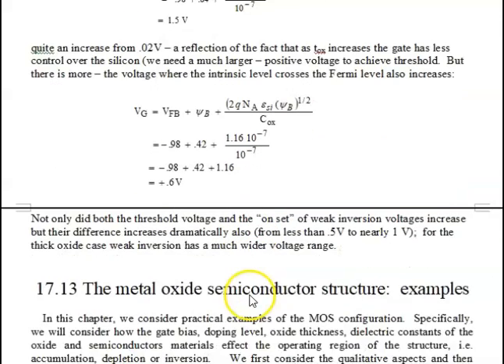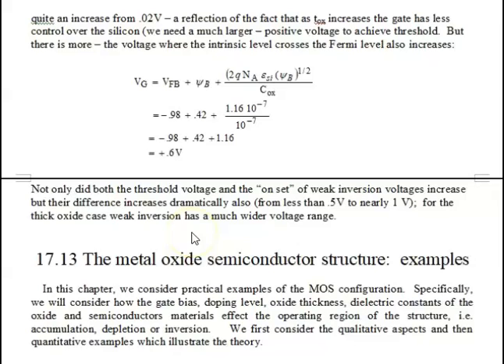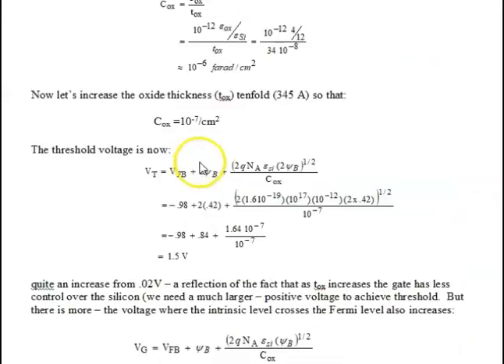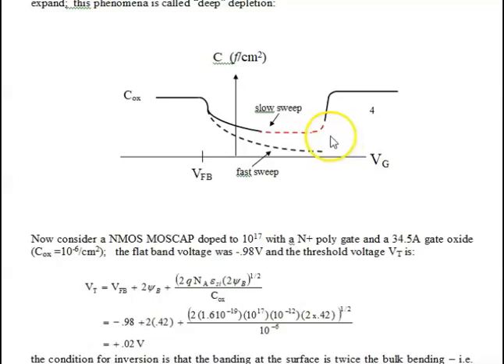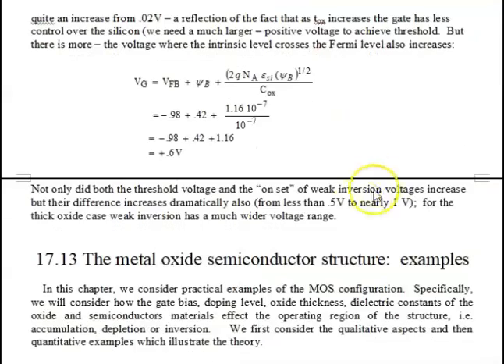So what's happened here is, and I'll just read this off, not only did the threshold voltage and the onset of weak inversion increase. Well, remember that the threshold voltage is 0.02, now it's 1.5, but the difference between the onset of weak inversion to the onset of strong inversion increased from about 0.46 volts, this region here, to almost 1 volt. That is big. So from less than 0.5 volts, it increases to nearly 1 volt. That is not good. That is not good at all. We want to make it smaller.